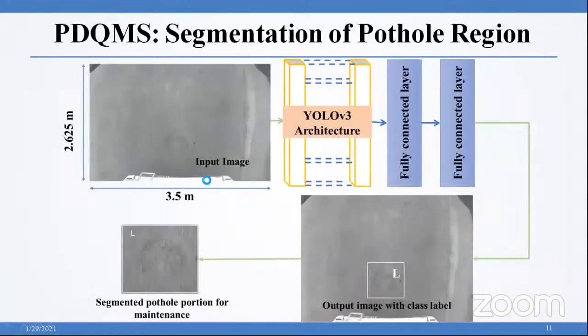After labeling, these images were then fed to the YOLO v3 architecture, and about 3000 iterations were performed. And at the end of the 3000 iterations, we have achieved a precision of 89.23%, and the network had identified the pothole regions, and a bounding box was marked on it, along with the class label. After that, a set of code was written in Python where the marked region will be segmented from the entire pavement image.